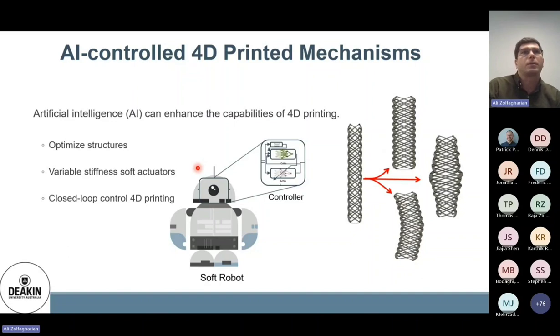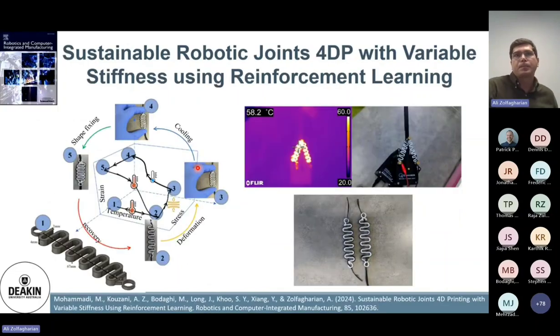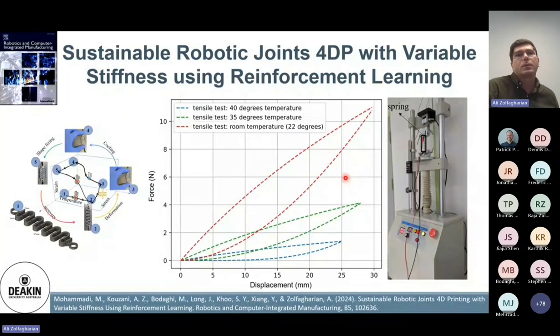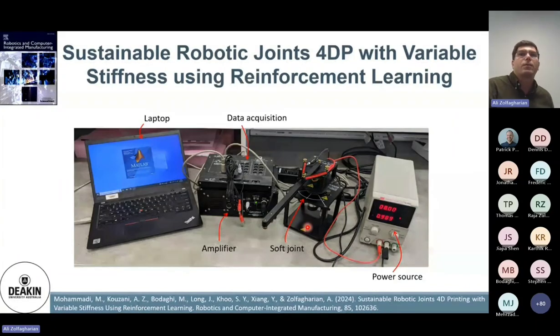And recently, in the project of my PhD student, we applied an AI-controlled 4D printing mechanism. As you could see, we use shape memory polymer and 4D printing of shape memory polymer in order to achieve different stiffness of the joint. In robotic applications, we just use these flexible joints here, and with 4D printing we could come up with different stiffness, and by changing the properties of the spring or the joint, we could achieve different stiffness for different applications in soft robotics.